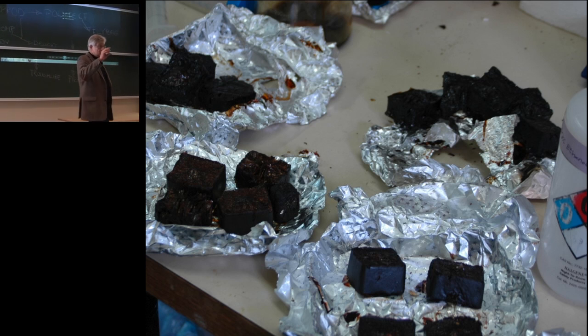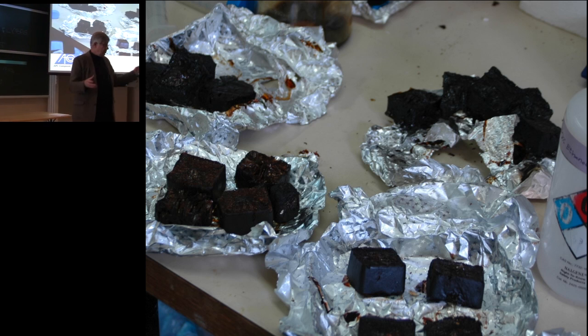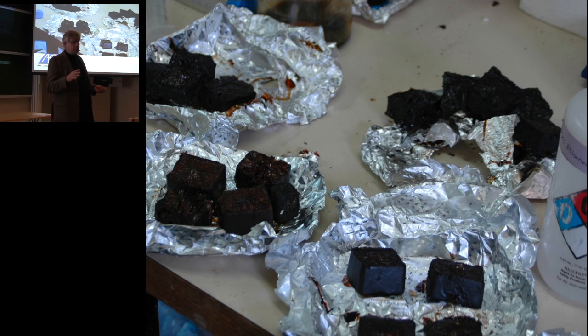And then I can use this light foam of 25 kilo for insulation, or I can infiltrate some kind of polymerization resin into it and get a much more stable foam. For instance, I can use the hemicellulose resin called furfuryl alcohol, which I talked about earlier, used as resin with the flax fibers. If I do the same here, I get a cellulose foam infused with hemicellulose resin: two different parts of the wood, but pure, no other things there. And this foam doesn't burn.